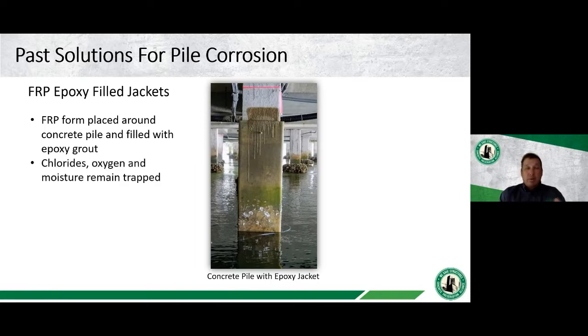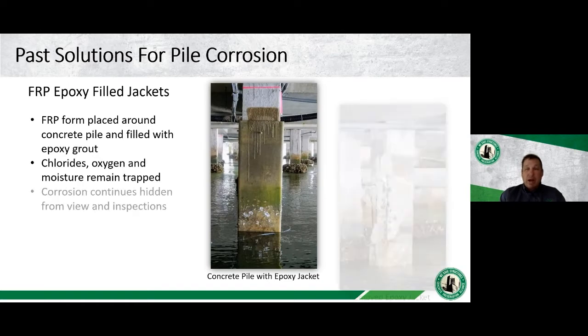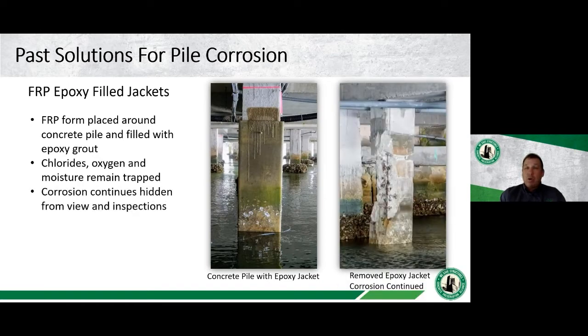What ends up happening is when you put that around there, there are still chlorides, oxygen, and moisture trapped underneath this jacket or this epoxy grout. And even with the chlorides and the oxygen behind there, it continues to corrode.